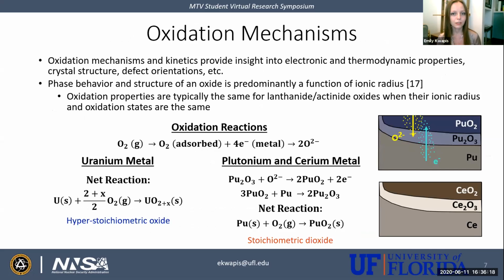So to approach this from a mathematical standpoint, I've decided to look into the oxidation mechanisms and kinetics of these three elements. Oxidation provides insight into the electronic, thermodynamic, chemical, mechanical properties of an element. And we know that the oxidation properties are the same for lanthanide and actinide oxides of the same oxidation states. And we do see this with plutonium and cerium, where they follow the same oxidation reactions to form a stoichiometric dioxide, while uranium forms a hyperstoichiometric oxide.